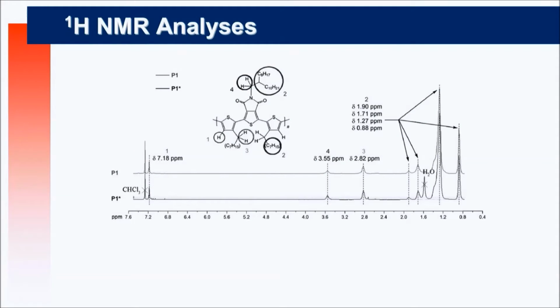Not only does it work, but we got higher molecular weight. So instead of 10 number average molecular weight, we got 55. And we think that these CH bonds here are not reacting because they are somehow sterically hindered by the side chain here. And we checked by NMR. We compare the Stille coupled polymer and the polymer obtained by direct heteroarylation. It's comparable. You just see some little peaks here which are related to what we call the end groups. If you have a low molecular weight material, the end groups become more important and you see those extra peaks in your NMR. So it's a well-defined alternating copolymer.